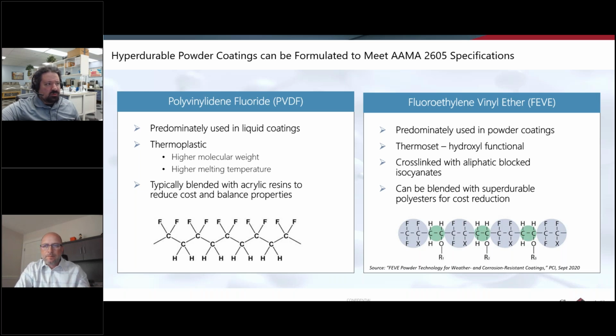The reason it's not as prevalent in powder coatings is that it's a thermoplastic as opposed to a thermoset. So it has higher molecular weight, higher melting temperature, and it's just more difficult to process using our standard powder processing equipment. It's a small part of the market, but they do exist: people make powder out of PVDF, compound it with the pigments and the additives to make it meet the specification, and then you can spray that on parts and bake it.